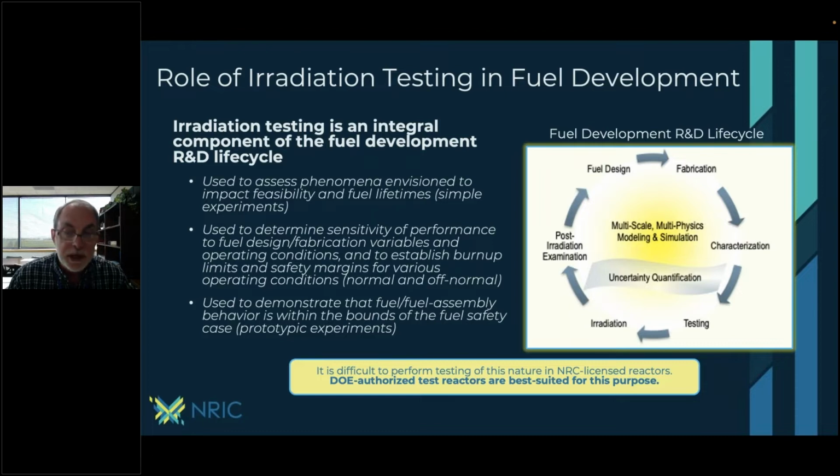Initial experiments are oftentimes very simple and often quick. As the design matures, irradiation testing is used to determine sensitivity of performance to fuel design, fabrication variables, and operating conditions, and ultimately to establish burn-up limits and quantify safety margins for various operating conditions, both normal and off-normal.